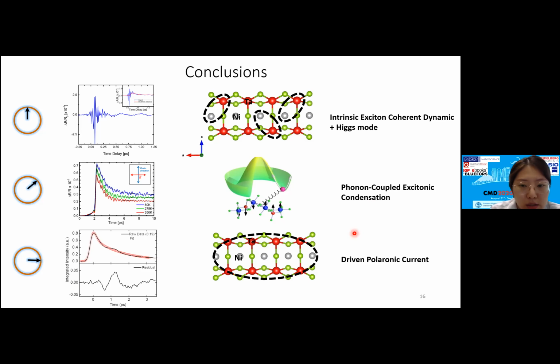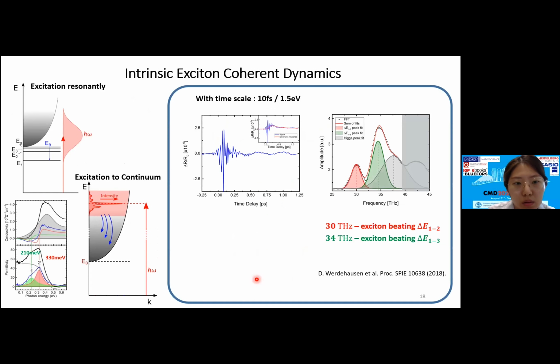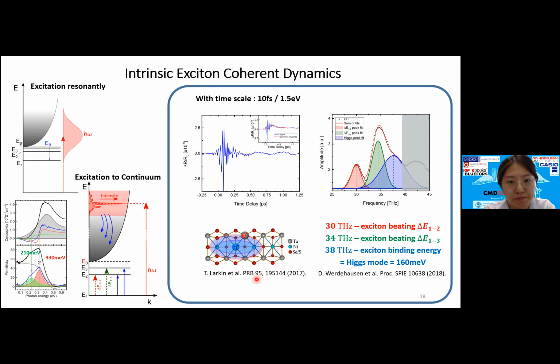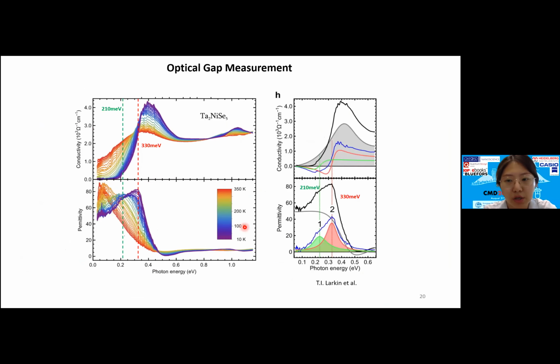Yes, actually, this polaronic complex is suggested in static optical measurements. Firstly, this is a static optical measurement, and it suggests excitonic levels. The excitonic energy level is not below the continuum, in the gap, but lifted up to the continuum. That means they suggested there is a strong phonon coupling to the excitonic state.